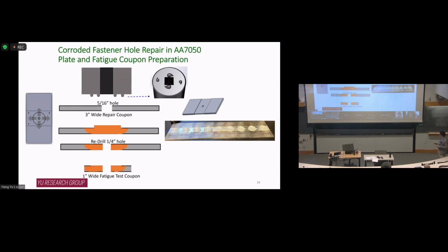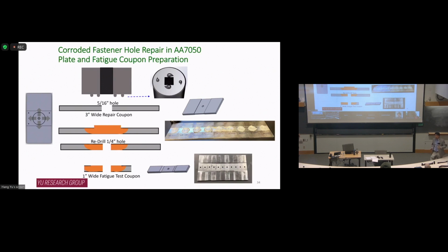Eventually we can fabricate them into fatigue testing coupons. Of course, with fatigue testing we need to take care of the statistics, so we have to make tons of coupons to make sure everything is consistent. Those are some examples we made. This is after deposition, so you have small caps on the top, and then we remove the excess material and re-drill the original hole size. I got 10 plus fatigue coupons I can test.